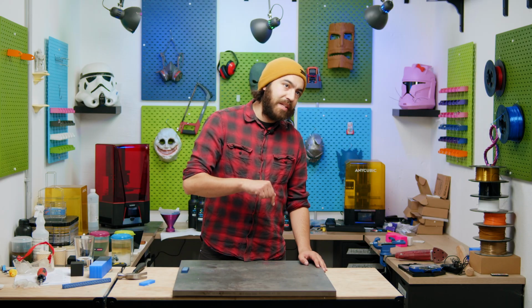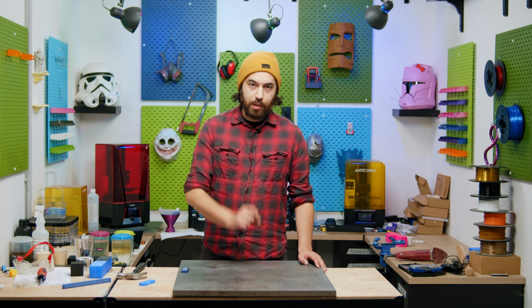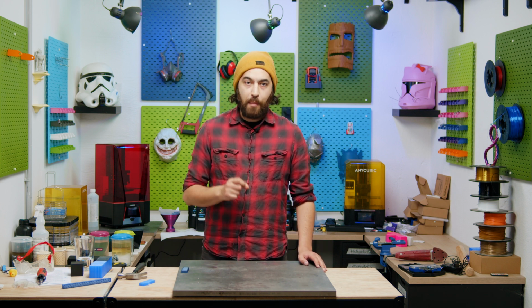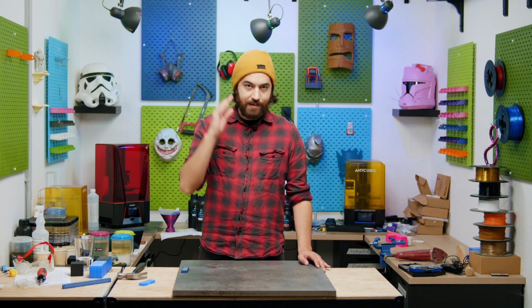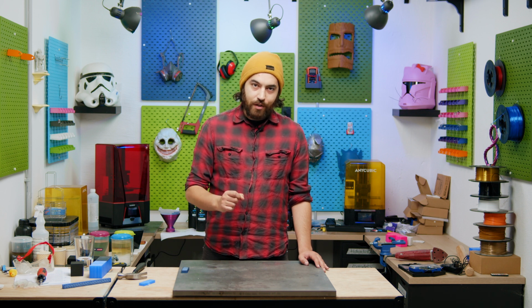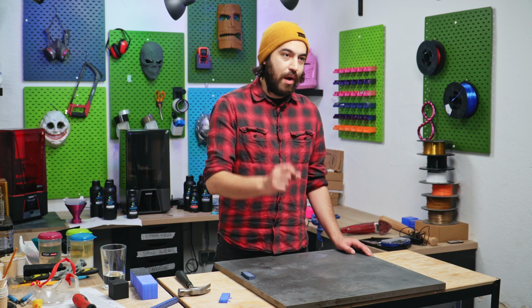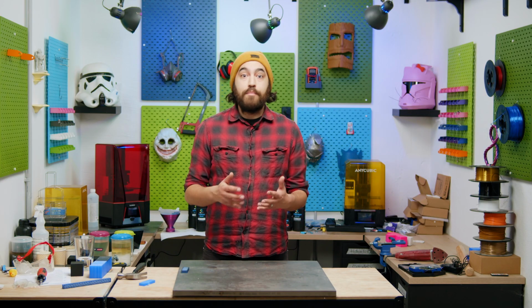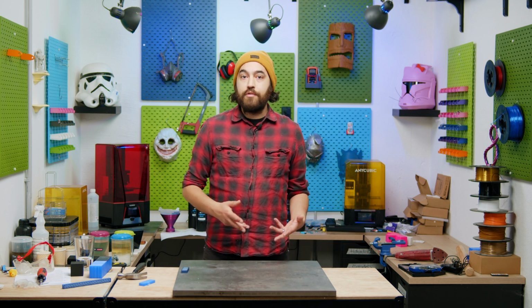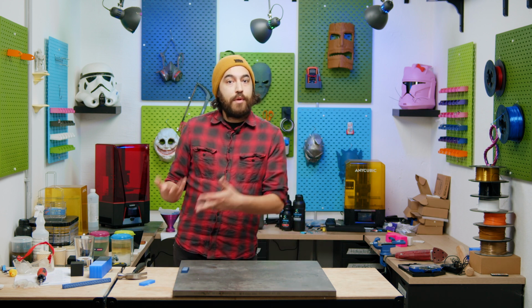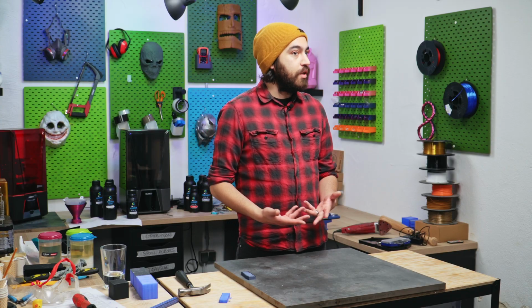So going back to multi-material use, Joel chose PETG and TPU because they have similar processing temperatures and similar properties. PETG and TPU are probably the stickiest filaments out there. And because of this, stringing is frequently a problem with them. But for us, that's really good because they're gonna be so sticky that they will bond together really well. So what advantage does mixing TPU and PETG actually have? Well, it will make PETG more impact resistant, and it will make the TPU more rigid, which is pretty useful.